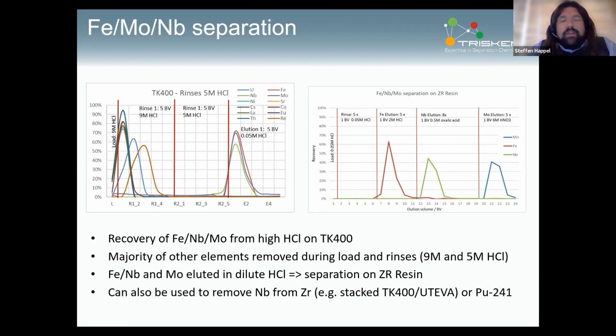Another application is actually something that we get from time to time. Niobium is an interference on the quantification of plutonium-241. So you can just use it to remove traces of niobium and zirconium from plutonium-241 samples before LSC measurement. That might be done, for example, using stacked TK400 or UTEVA cartridges.